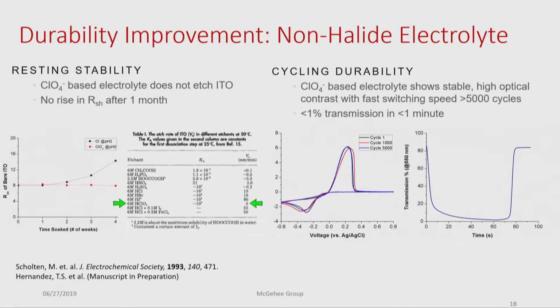We were able to rectify this problem by switching to a non-halide-based electrolyte, specifically ones that rely on perchlorate ions. So you can see here, when we use this non-halide electrolyte, we see no change in the sheet resistance over the course of a month. And this proves that our non-halide electrolyte is not etching the ITO surface. And this has been shown both experimentally in our lab as well as in previous academic literature.